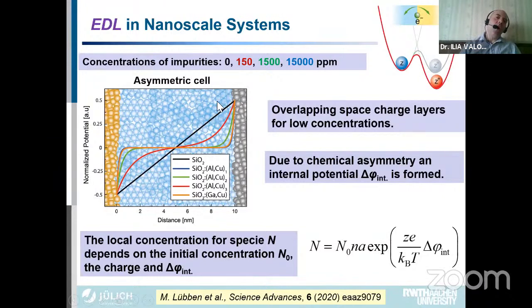Then you have overlapping space charge layers. So this means that your whole material is a space charge layer. And then you see how potential goes through. And also here, when the concentration is increased to 1,500 or 15,000 ppm, then you start to go back to the classical situation, which I have shown in the previous slide, where you have almost constant potential within the electrolyte. So everything depends. It's not only a matter of size, but also a matter of concentration of mobile charges.